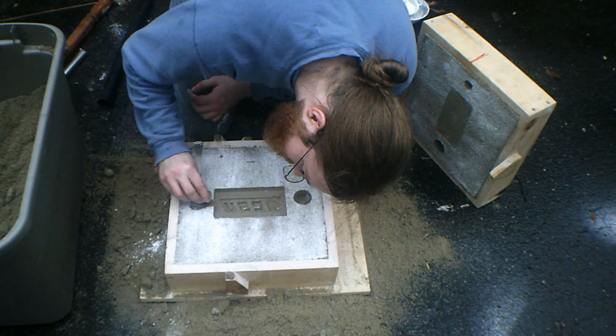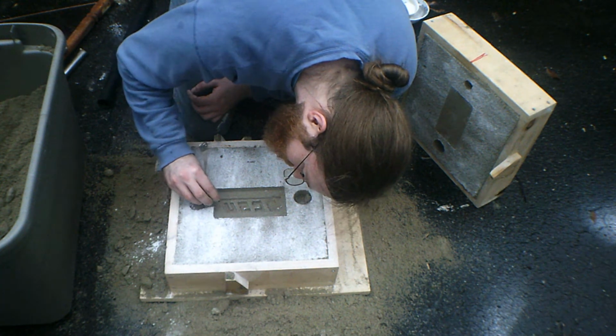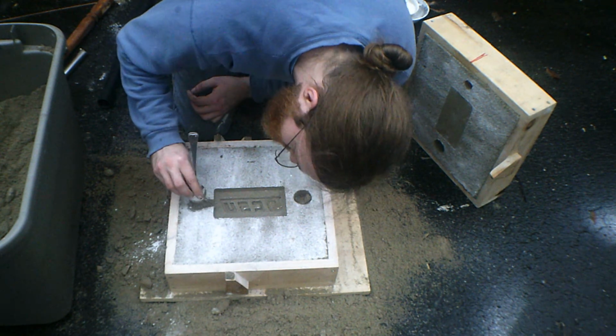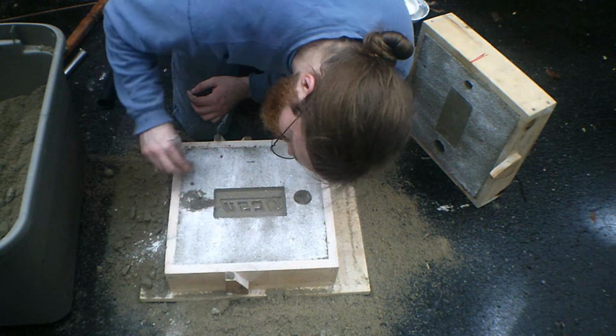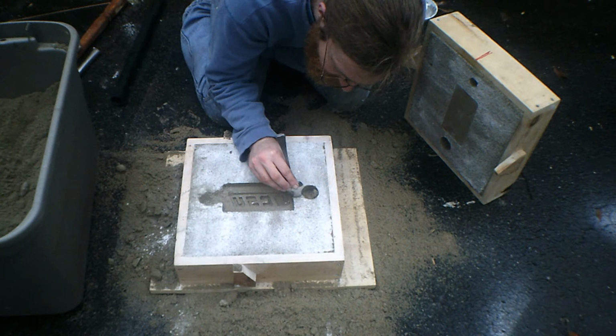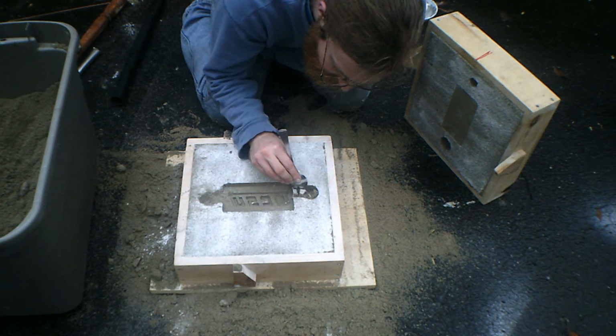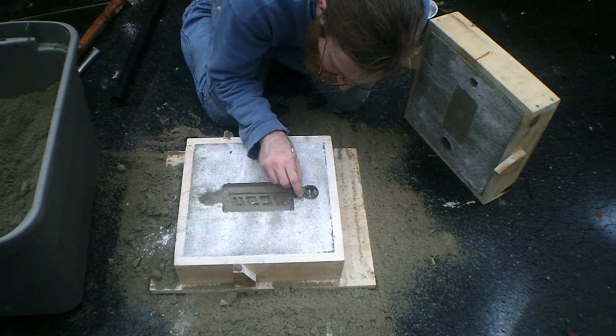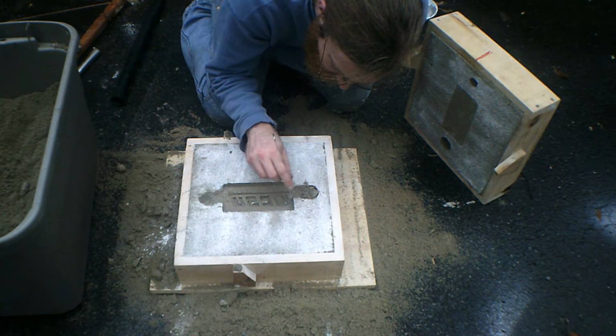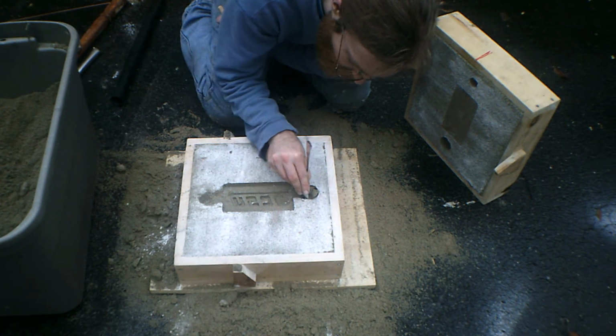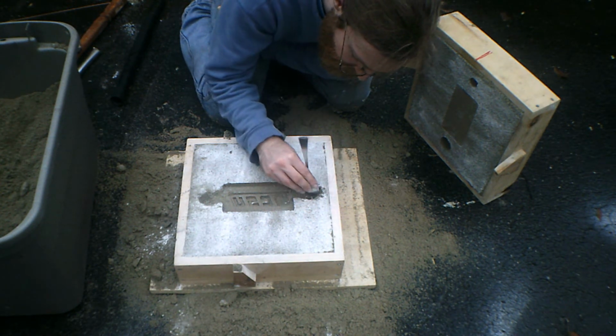After that, you need to create the gates between the sprue and the pattern and the riser. Now, the mold here is in the shape of the finished part, and I had something to mold the sprue and riser around, but the channel that the molten metal goes through, it's silly to try to mold, so you just scoop out what you don't need.